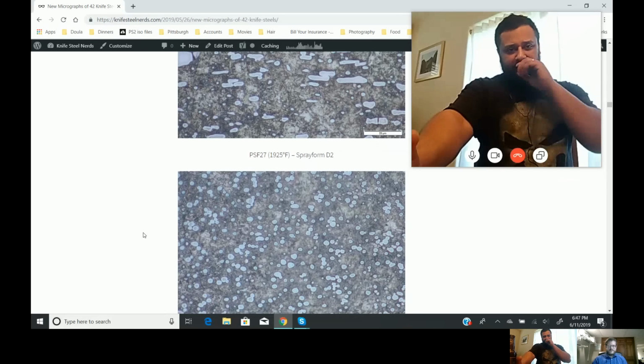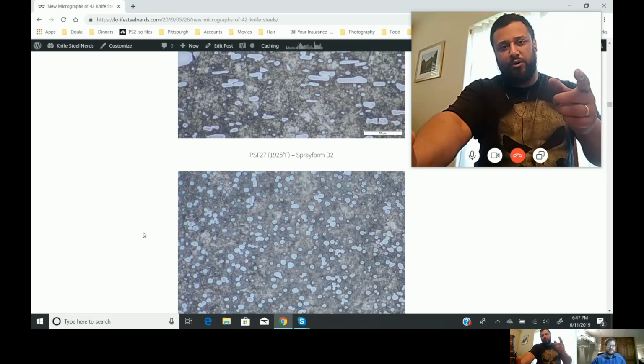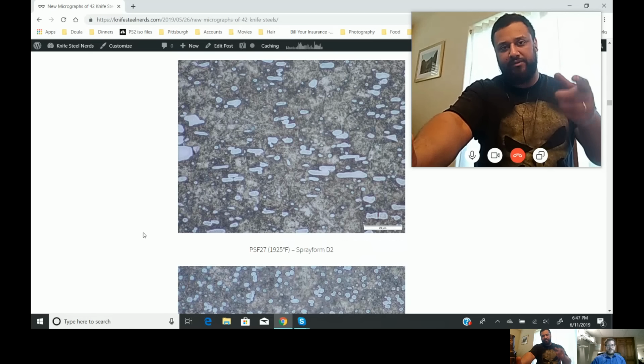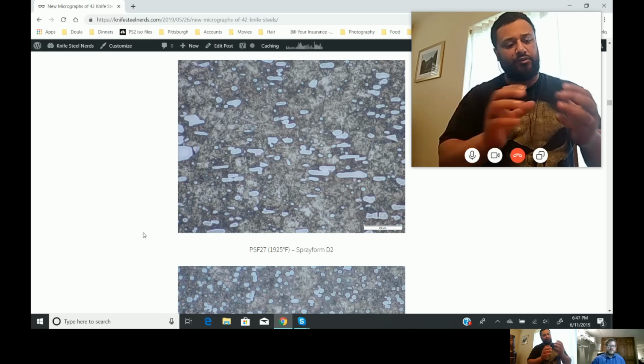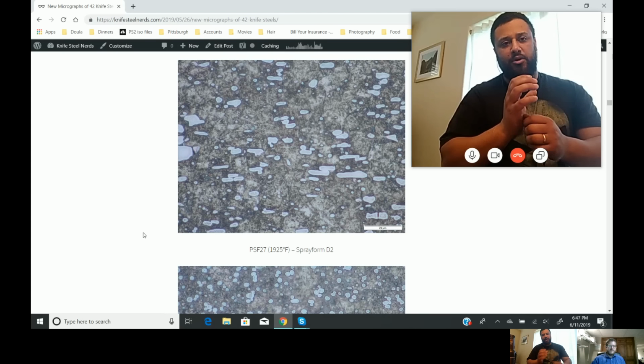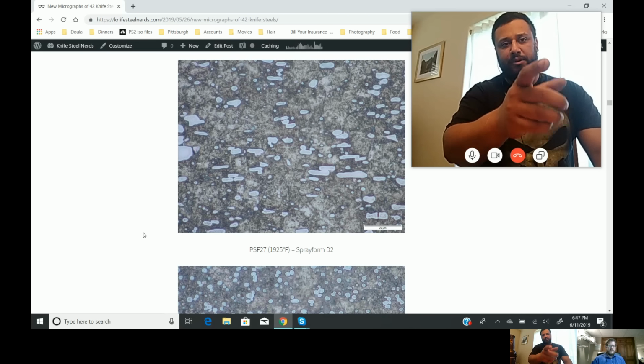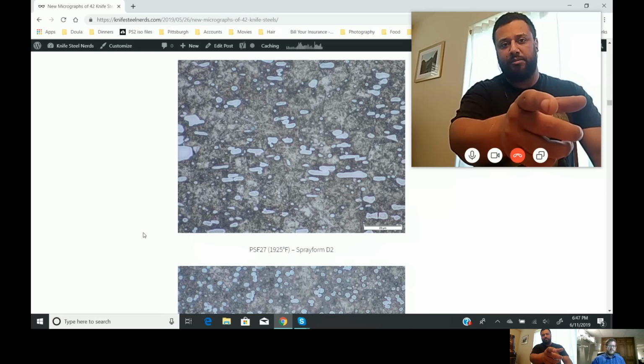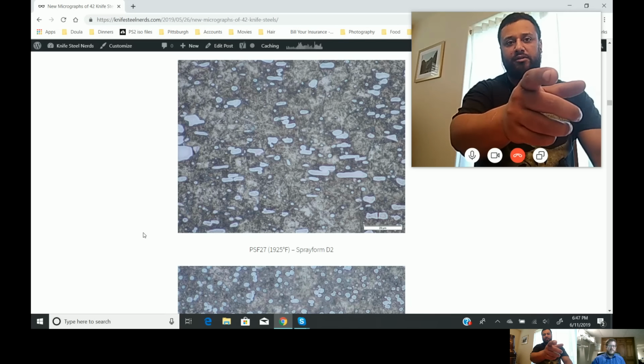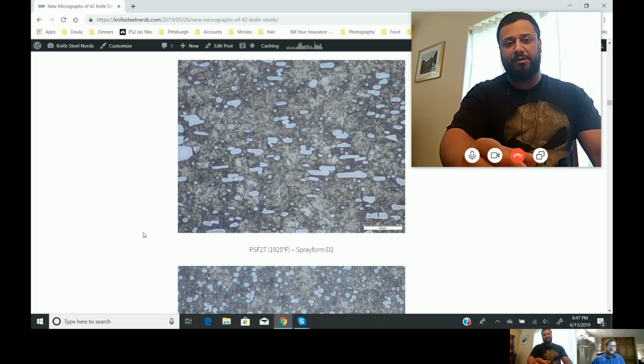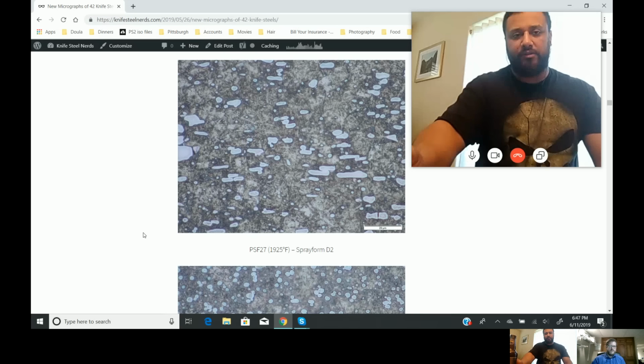Real quick, Larrin, I'd like to share the scuttlebutt about why spray form might have some advantages. Just a theory, we would have to test it more, but people sometimes like spray form better than the powdered steel because they feel it accentuates a coarser edge a little better than the finer carbides of the powdered steel. And why people like D2 is they like the coarser aggression that they feel with a low grit edge from the bigger, blockier carbides. This gives you a nice in between from the powdering process, which accentuates a polished edge. This one's in the middle, where you still have a little more toughness from finer carbides, but it's just hearsay without further testing, right?